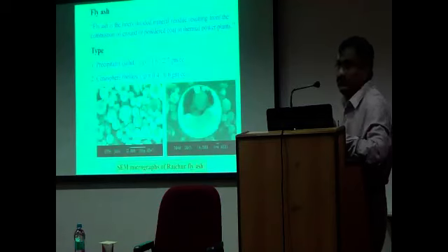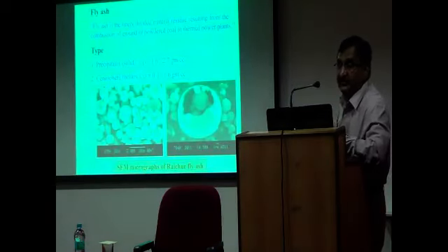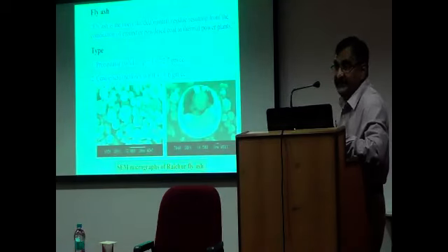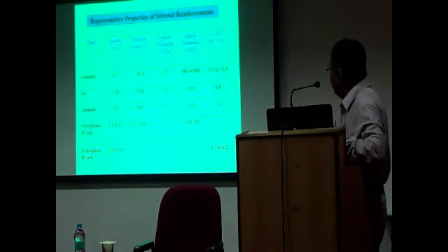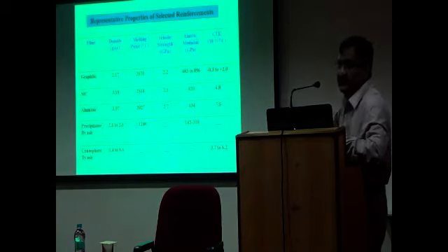This is how this reinforcement looks under the scanning electron microscope, at 40 to 100 microns. You can see the fly ash is available, the spherical one is a hollow one. Its density is very low. So when you produce this composite, it will give you very low density. So it's an advantage.